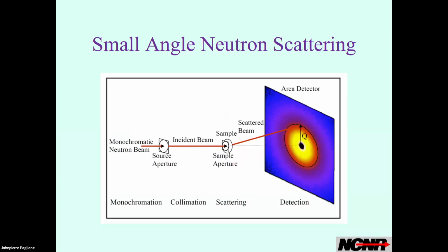And then to look at the behavior of the magnetism in competition with the superconductivity, you need to do small angle scattering, because the London penetration depth, which tells you about the Meissner effect, is typically hundreds to thousands of angstroms.